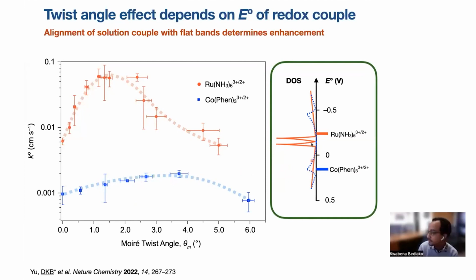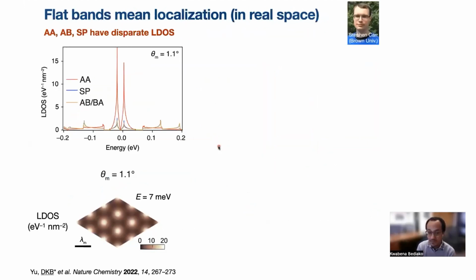So all of these taken together was quite encouraging, that we can understand the origin of this effect, at least to a first order approximation. To go a little bit deeper, we have to recognize what these flat bands mean. Flat bands in reciprocal space means localization of the electron wave function in real space, and this has been known for a while, but just to show you some of the calculations here as well.